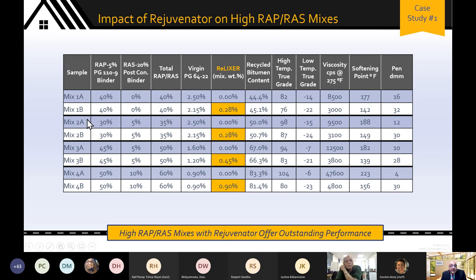Let's look at mix one. Mix 1A has 40% RAP, no rejuvenator. Mix 1B has the same 40% RAP with 0.28% by weight of rejuvenator. This is extracted data. You make your mix, you extract your bitumen, and you look for all these properties. Let's focus on viscosity. We're able to see that your viscosity is reduced almost from about 9,000 to about 3,000. Let's look at PG low grade, something that folks in New Zealand or USA or Canada may look at. You're taking this material, which had a minus 14 grade, and reducing it to a minus 22, which is quite a common grade across much of North America.